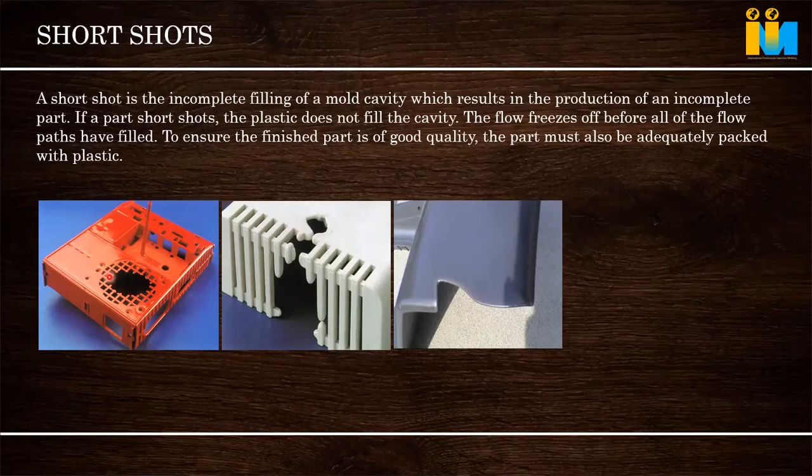Sometimes the machine nozzle size will be so small that whatever pressure we are giving in the machine, the nozzle itself will be consuming. Nothing is coming to the runner, the gate and the part. So we have to check that. In the molding machine, I told you up to the gate 30 to 40 MPa is the best pressure drop. When material is coming through the nozzle, there is a pressure drop happening in the nozzle also. Generally, it should be around 10 MPa.